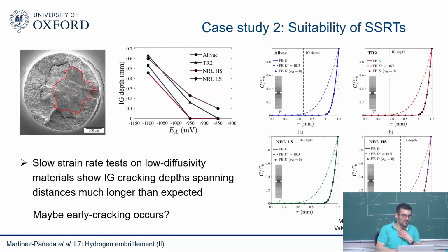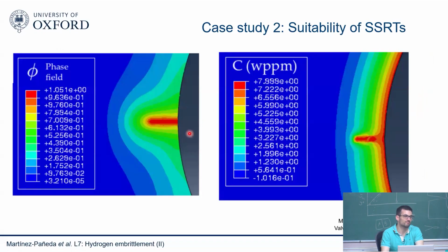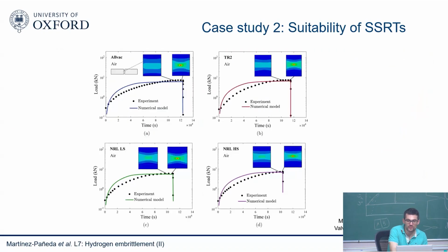And the hypothesis we had is maybe you get a bit of cracking, and then the hydrogen follows the crack, because the electrolyte will immediately enter that crack, and therefore you get the crack exposure. That is the thought. So we tried to do these simulations. First we started by simulating the ductile failure, the case in air for these 4 materials. We used the phase field model and modeled the ductile failure. We're not resolving any micromechanisms, but it's an elastoplastic fracture model with some toughness, so why not? I think we calibrated the toughness with the experiment, and it was a good agreement.